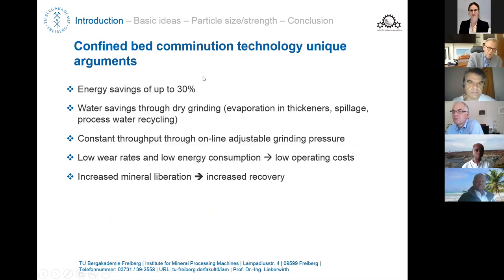So confined bed comminution is unique due to energy savings, maybe up to 30%. In practice, I would go to maybe 10 to 15%. Still interesting. Water savings, throughput, low wear rates, low energy consumption, increased recovery.